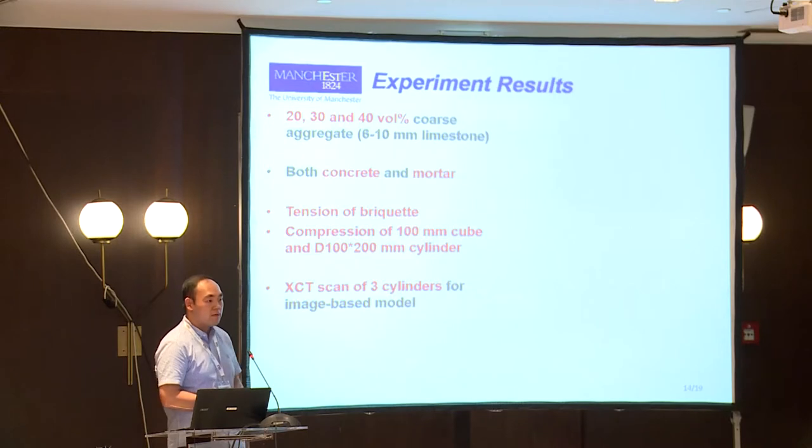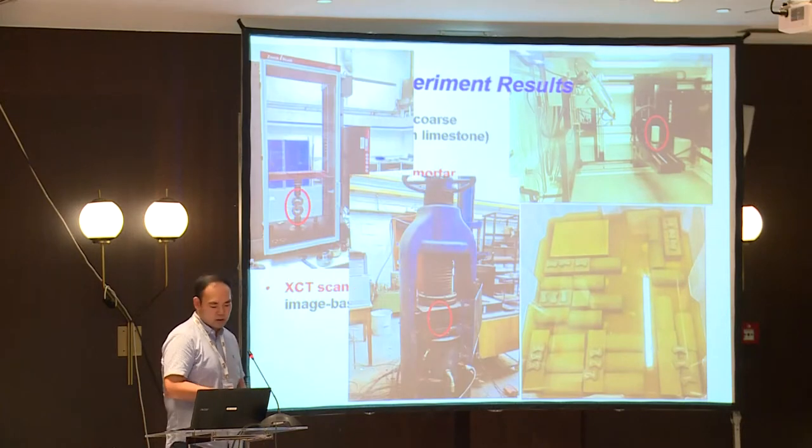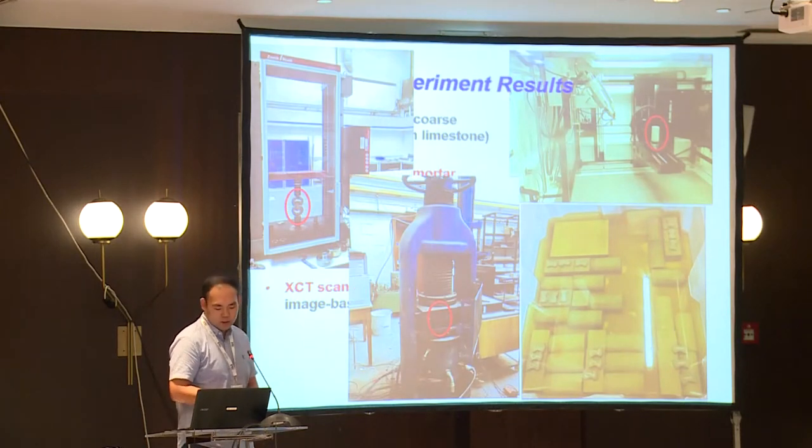So based on the validation results, I cast both mortar and concrete specimens to obtain parameters for my model, such as Young's modulus, tensile and compressive strength. After 28 days aging in water, the three cylinders were scanned to obtain the image-based model. These are the tension and the compression machine.